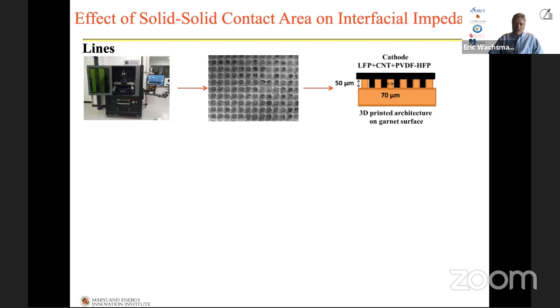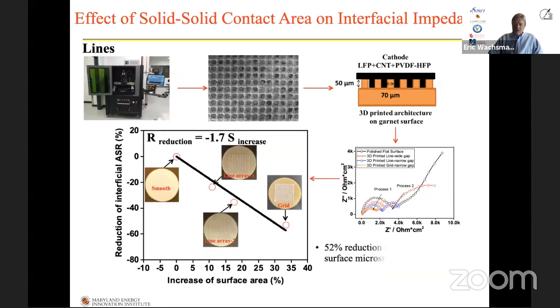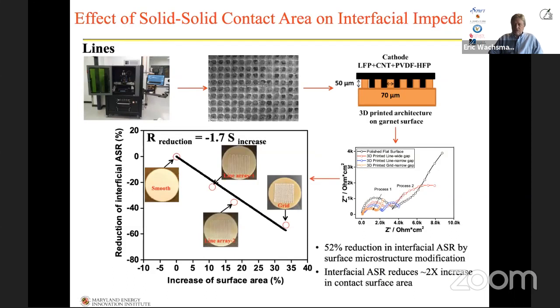These are lines here. And so again, they're printed. You can see the SEM image here. We're now filling this thing with a cathode material. We can measure the impedance of that. And these are the arcs from the electrochemical impedance spectroscopy. And this is a plot of the reduction in interfacial area specific resistance versus the increase of the surface area.